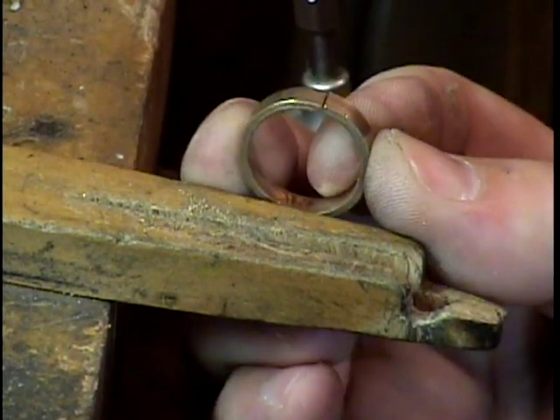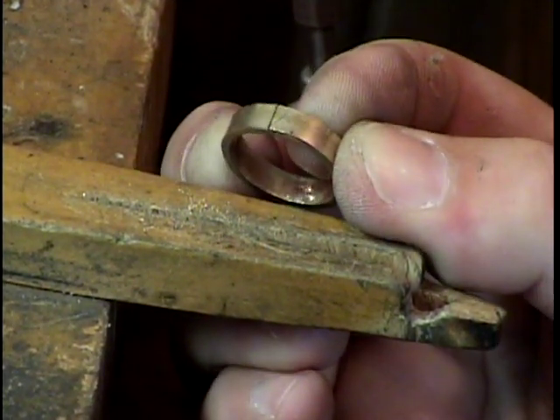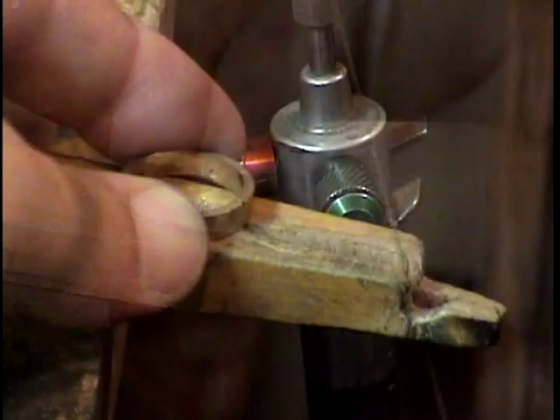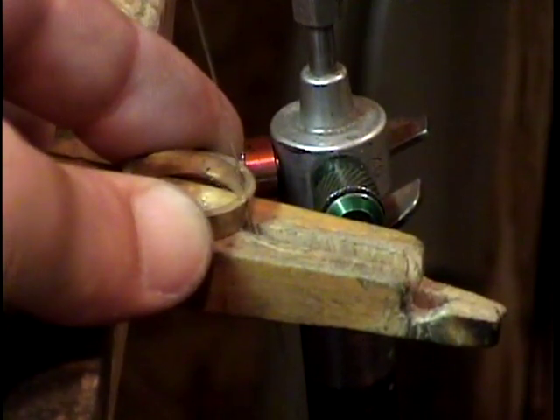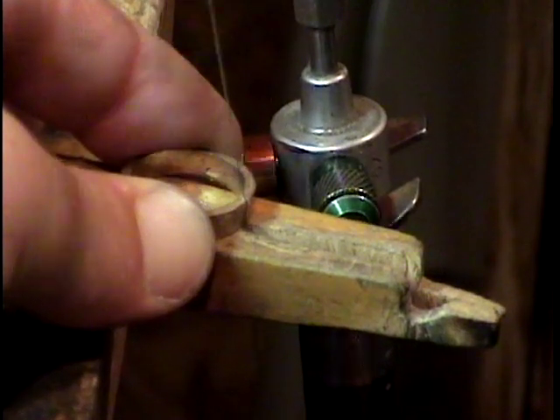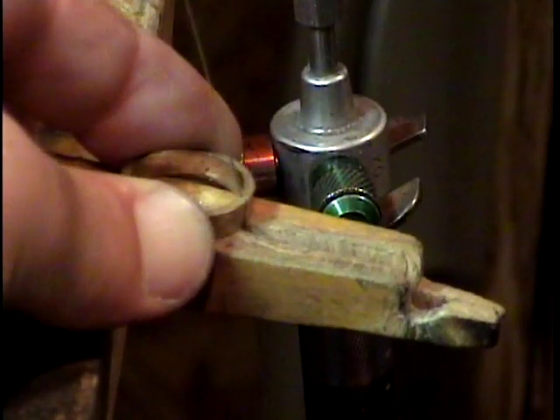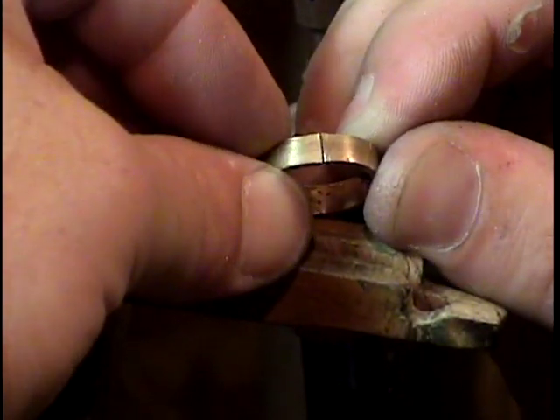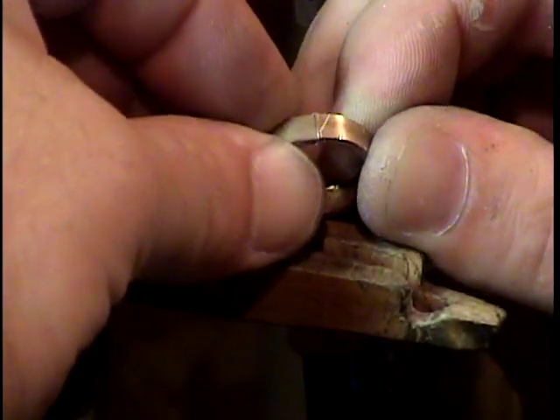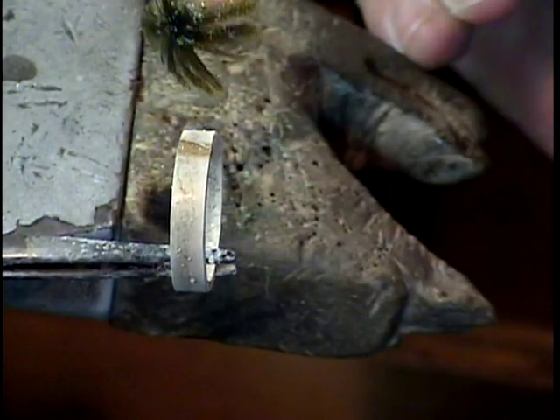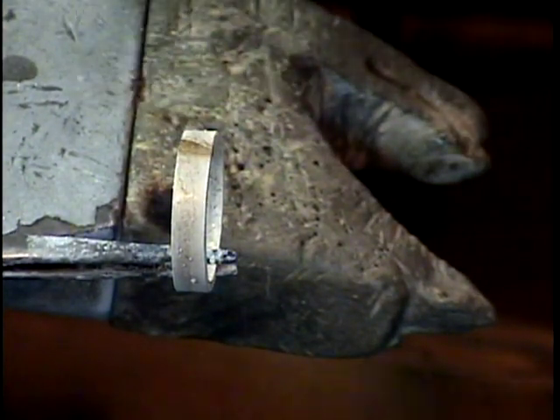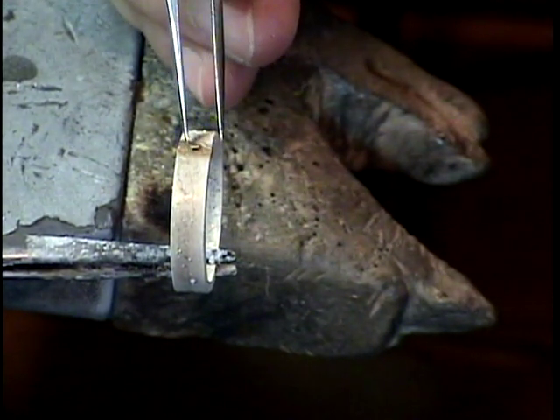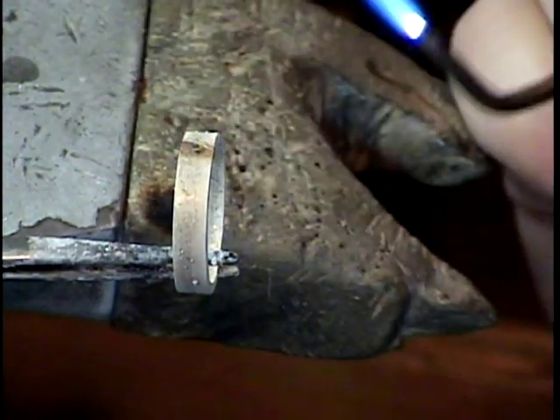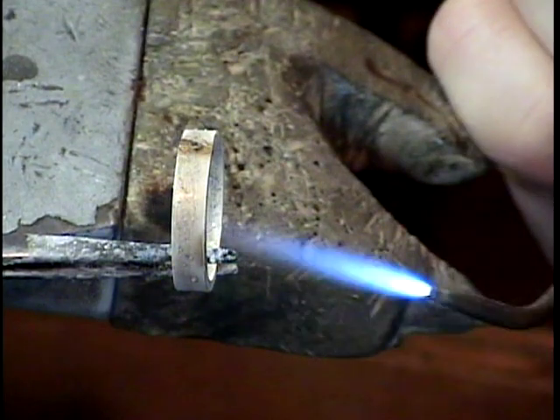Having filed our freshly cut end flat and manipulated the bends so that the ends are lined up, we fit the joint by running the saw blade through the unsoldered joint. This will ensure a perfect, flat, end-to-end fit and will create a very strong bond when flowed with hard solder. This works great for a sizing joint, and though that's what this looks like, it's actually the top of our opal ring. It'll all become clear soon.